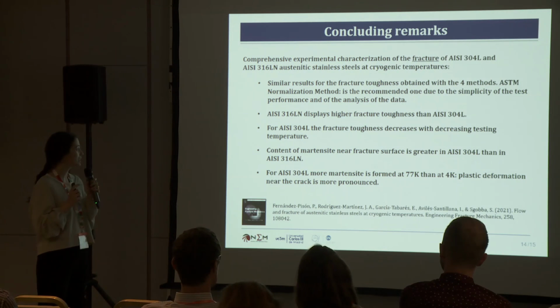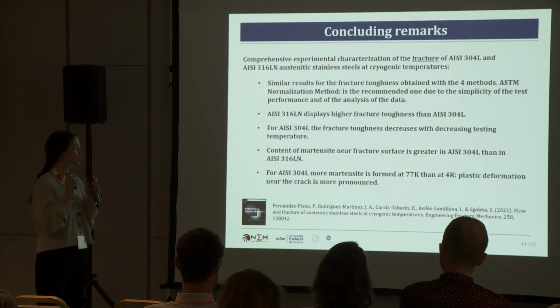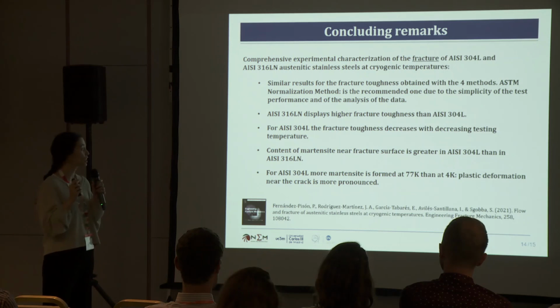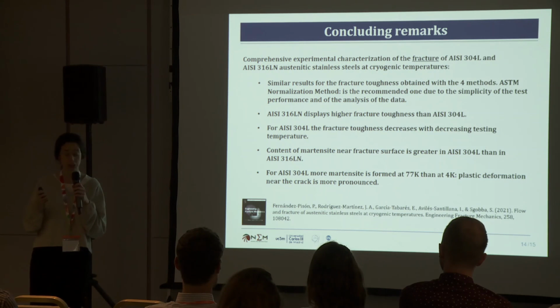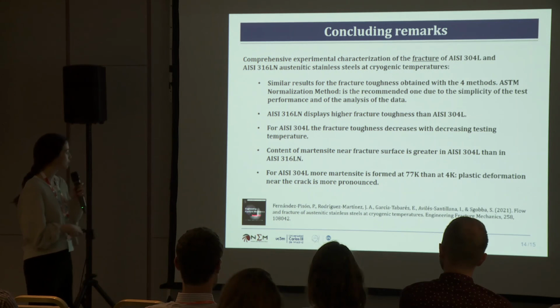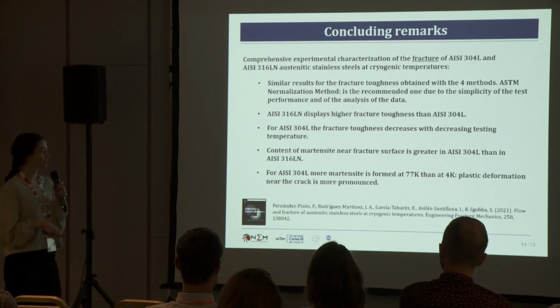And regarding the martensite, the content of martensite was higher for the 304L than for the 316LN, and for the 304L it was higher at 77 than at 4 Kelvin. If you are interested in all this experimental data, we have published these results in this paper in the Journal of Engineering Fracture Mechanics.